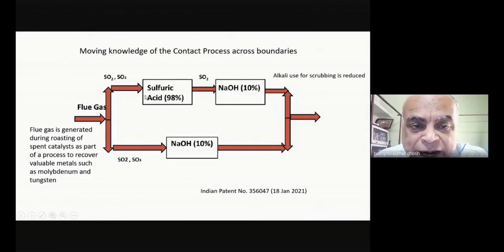So we said by doing this, we will not only be able to remove the SO3, we'll also get sulfuric acid, which is required in the process, and it reduces greatly the amount of alkali that you require to subsequently scrub the SO2. We were forming something like a 40-60 ratio of SO2 to SO3. So there was a huge reduction in the usage of alkali. And you also got sulfuric acid, which you could reuse in your process. So what did we do? We moved knowledge of the contact process into what? Into flue gas.